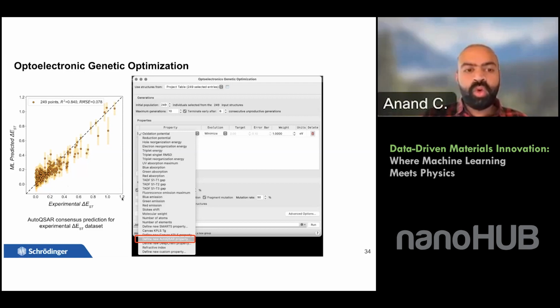So we can actually load all these molecules into the genetic optimization panel. So we have an initial population of around 249 molecules. And we choose that we want to minimize the delta EST value calculated using AutoQSAR. And we ask the genetic optimization to randomly mutate these fragments to come up with new ideas for new chemistries that minimize this particular value.